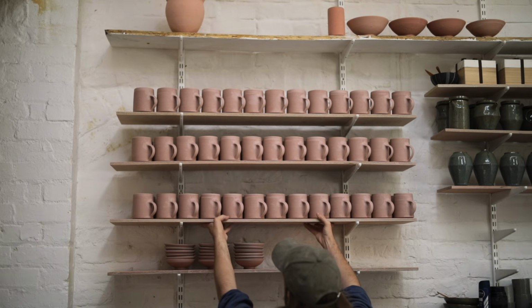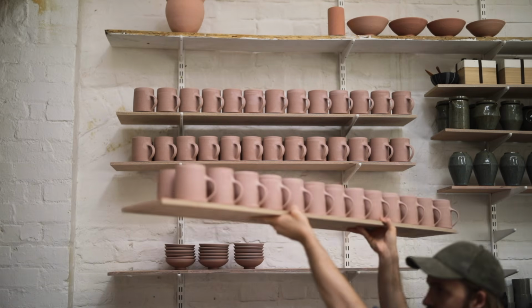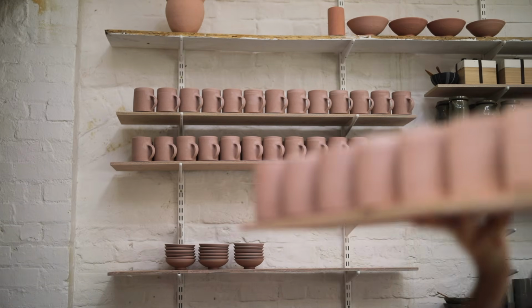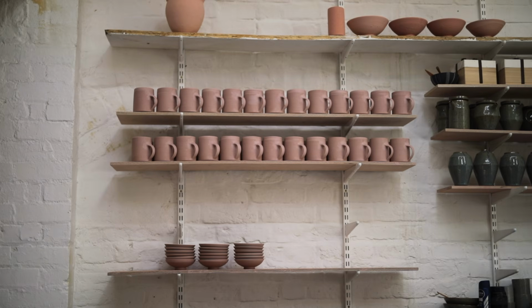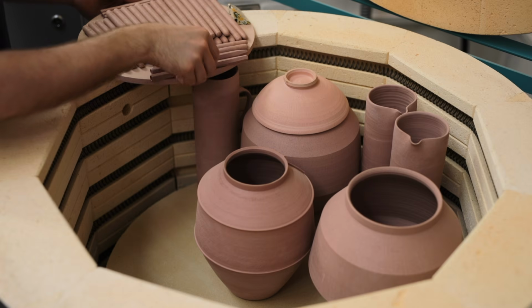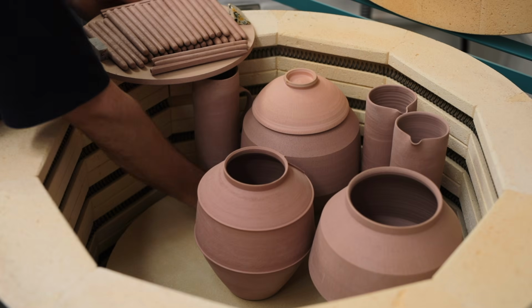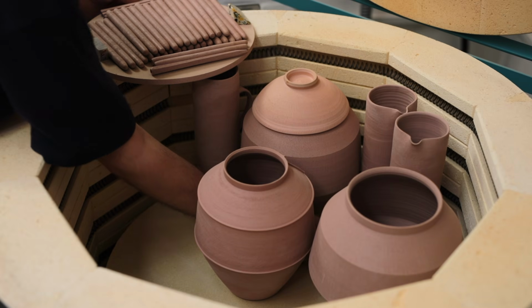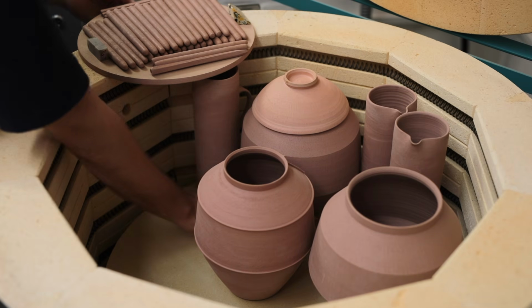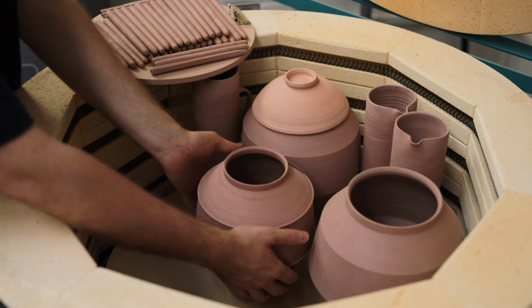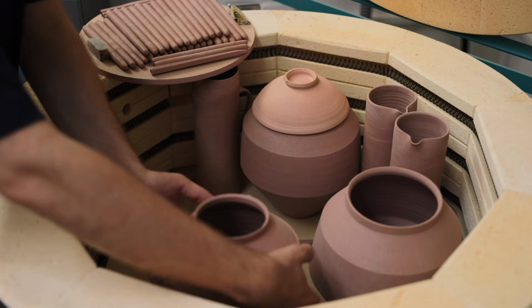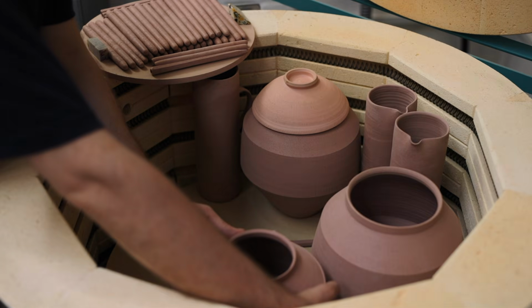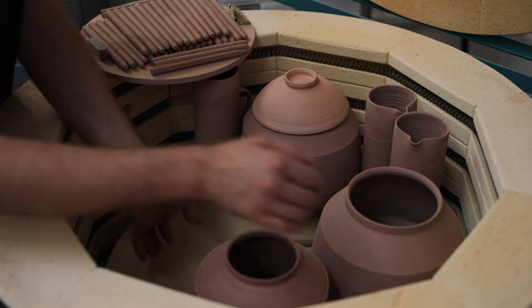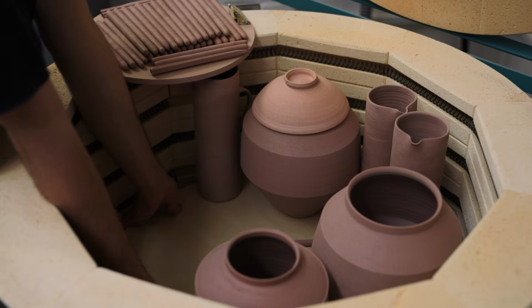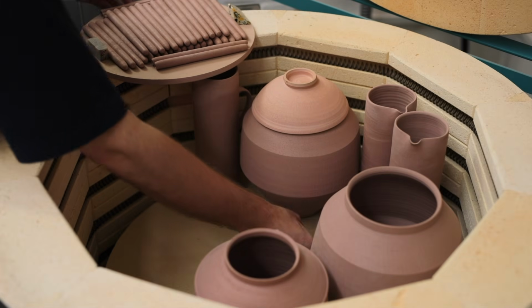But before I can do any of that, I need to do some bisque firings in my electric kiln. This is a process that changes what is clay at this point, that's bone dry and unbelievably fragile, into ceramic as the material undergoes quartz inversion at 573 degrees Celsius. This change is irreversible, and it makes the clay much stronger and also porous, which is a necessary attribute for when they need to be glazed.